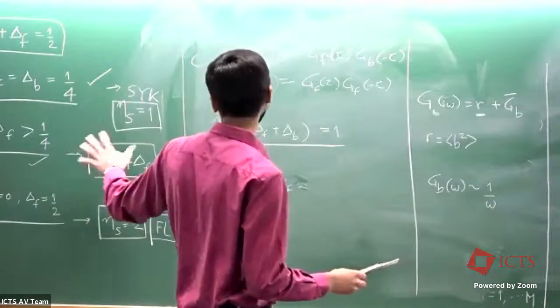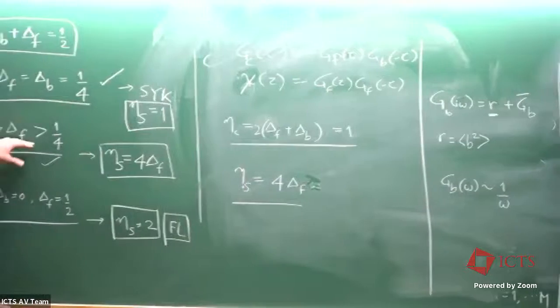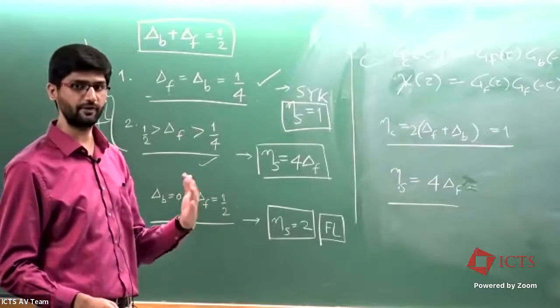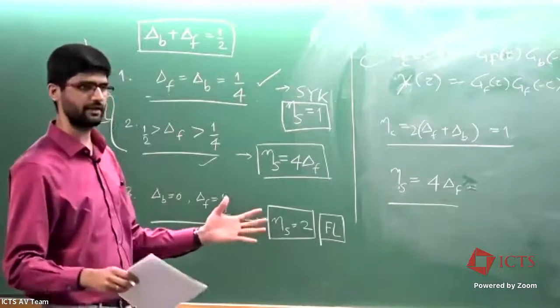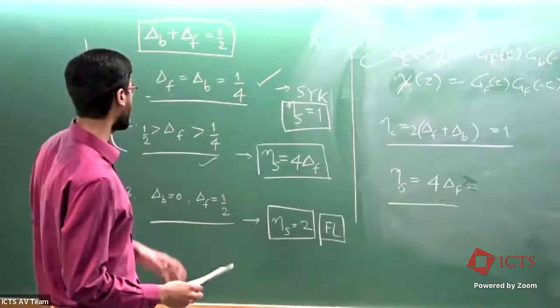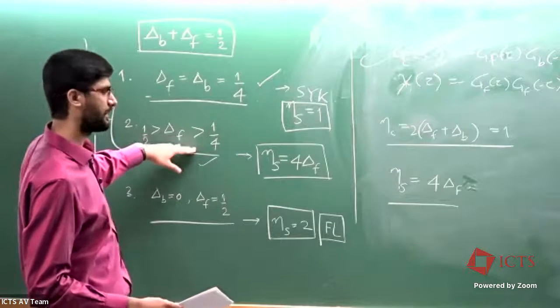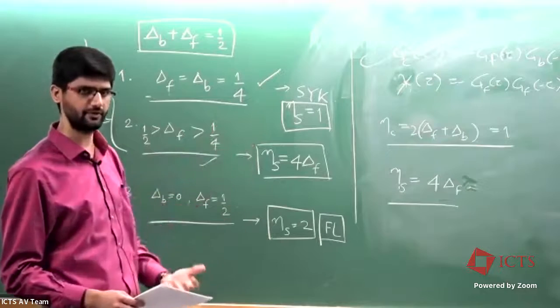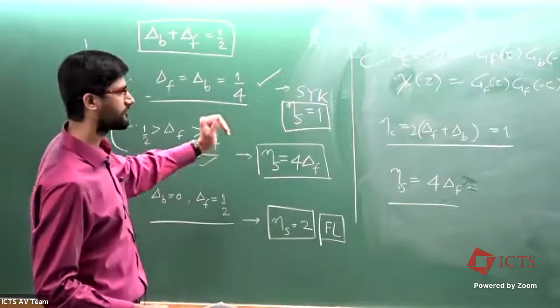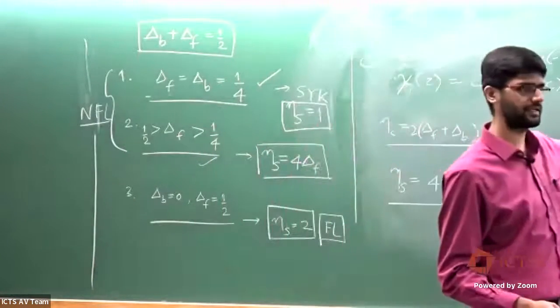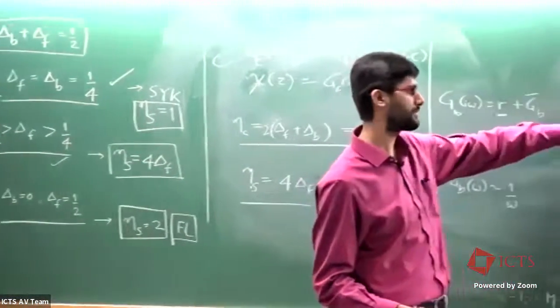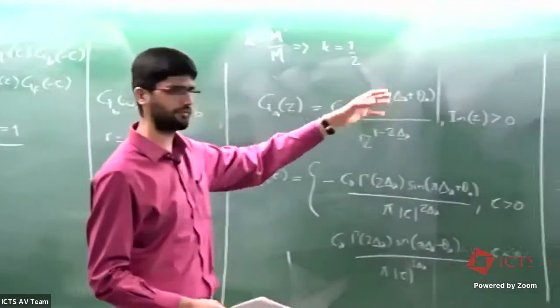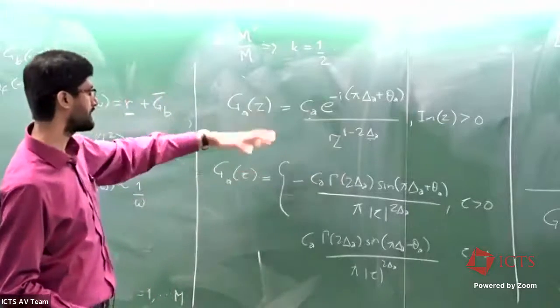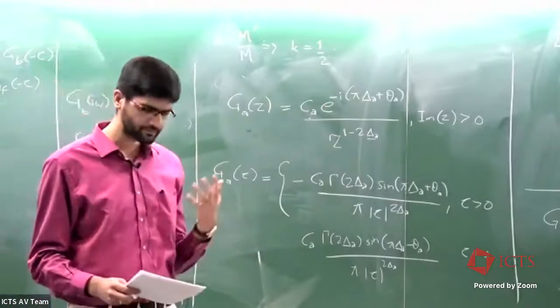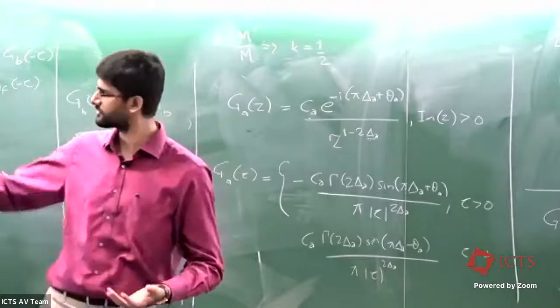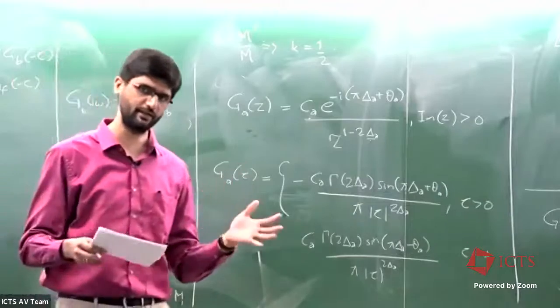Okay, so then we have these two solutions, and the argument is that this is the solution that describes this non-Fermi-Liquid phase with T-linear resistivity in a finite doping region beyond this P star. And the rationale for why this phase could be a good candidate for this observation is that the low frequency ansatz I'm considering is a very general solution. When I wrote this solution, I have not fixed any deltas or thetas. And you can show that this solution essentially has the same time reparameterization symmetry that the SYK type solution has for exactly delta equals 1/4.